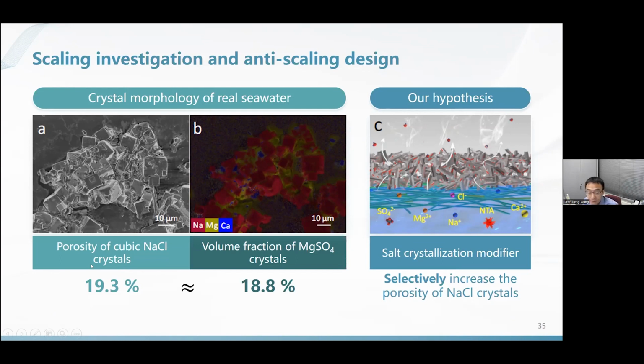Now, the troublemaker in the real seawater is magnesium sulfate. And magnesium sulfate crystallizes at a later stage. When it does so, it occupies all of the pores previously formed by those sodium chloride aggregates. So by the end of the crystallization, magnesium sulfate blocks all of the pores of the sodium chloride crystals. So without any pores, there's no water transportation channel. Therefore, there's no evaporation at all. The whole system breaks down at that point.